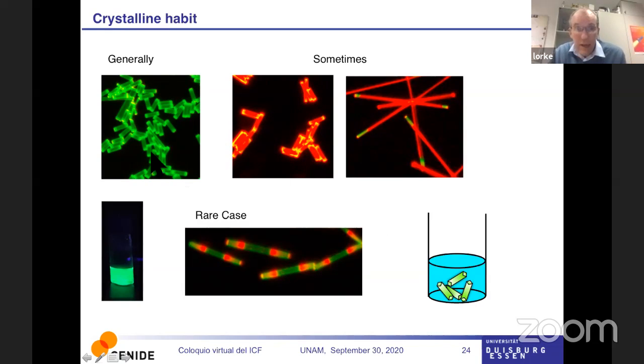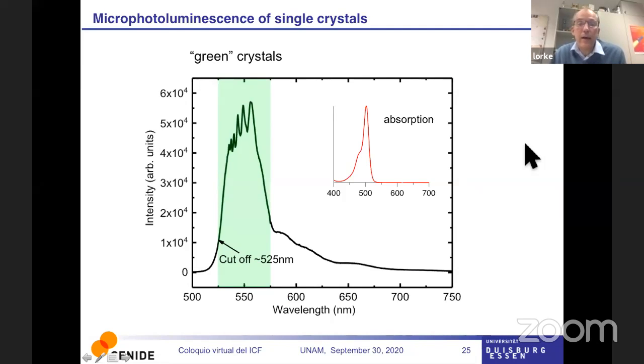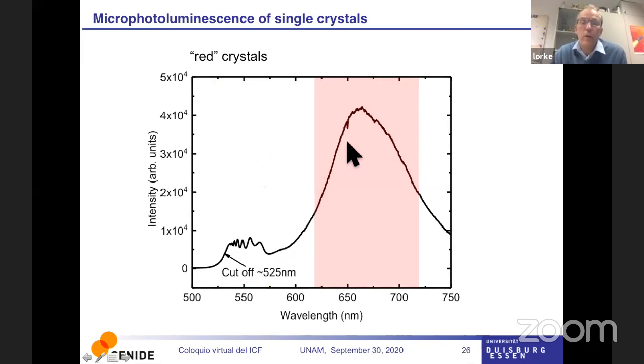And this is the same stuff. This is absolutely the same stuff. And in rare cases, you can really tell that because in one crystal you have both crystal phases. We looked at the green crystals, and you see a nice luminescence in the green. And we looked at the red crystals, and we saw a nice luminescence in the red. And we were trying to understand why you have these two phases.